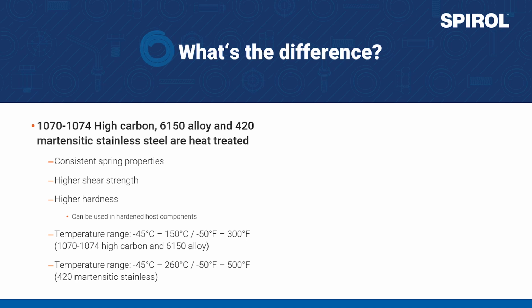In terms of operating temperatures, once heat treated, these materials will provide proper performance at temperatures ranging from -45 to 150 Celsius or -50 to 300 degrees Fahrenheit for high carbon steel and alloy, and as high as 260 degrees Celsius or 500 Fahrenheit for the martensitic stainless steel.